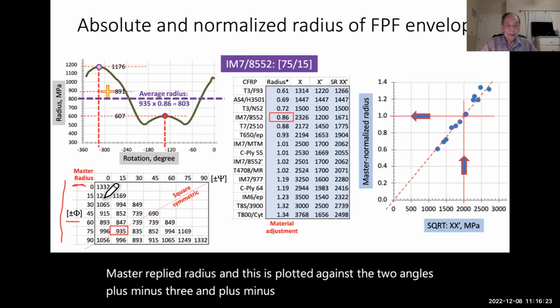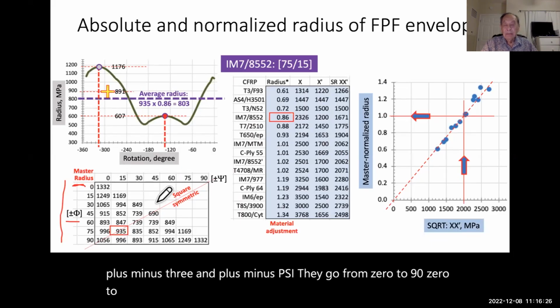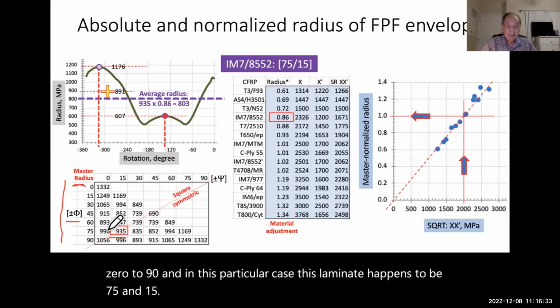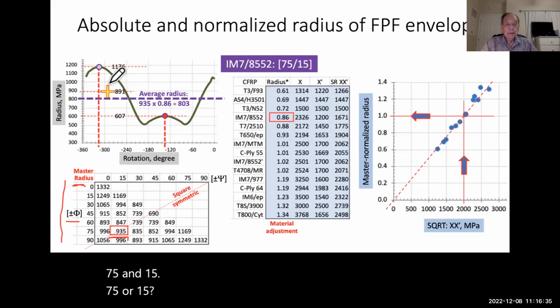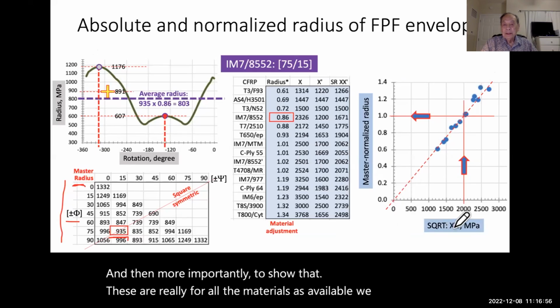They go from 0 to 90. In this particular case, this laminate happens to be 75 and 15. This shows the variation of the radius, and more importantly, that for all the materials available, we have a very simple relationship as a function of square root of x prime.